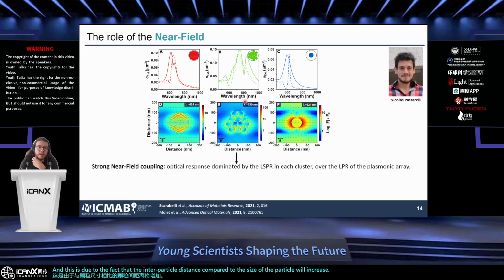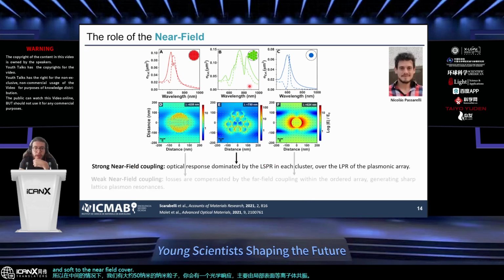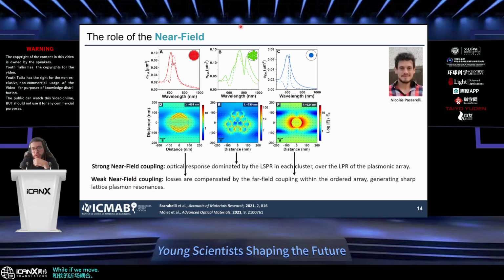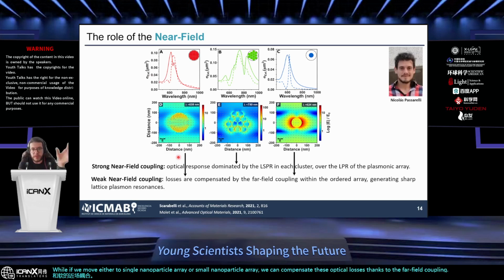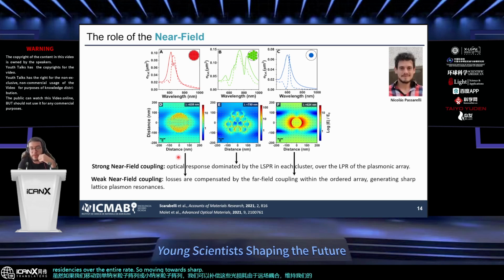And so in the middle case scenario, where we have around 50 nanometer nanoparticles, you will have an optical response that is dominated by the localized surface plasmon resonance of the cluster, and so by the near-field coupling. While if we move to either single nanoparticle arrays or small nanoparticle arrays, we can compensate these optical losses thanks to the far-field coupling, sustaining our resonances over the entire array. And so moving towards sharp lattice plasmon resonances.